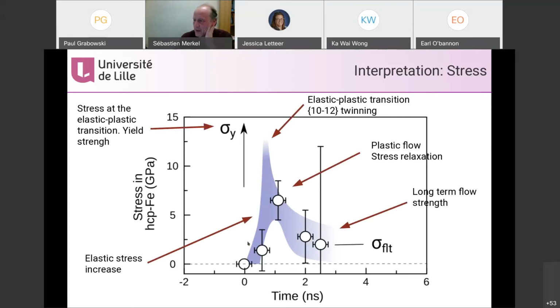I think what's happening is as the shock is coming into the sample, you get a big increase of elastic stresses, until enough defects are generated to activate plastic flow, plastic deformation. Then you get a transition from elastic to plastic behavior at the yield strength, and then plastic relaxation through 10-12 twinning. As you activate plasticity, the polycrystal can relax stresses, and so it goes down to what I call the long-term flow stress, which is much lower than the peak stress at the onset of plasticity.